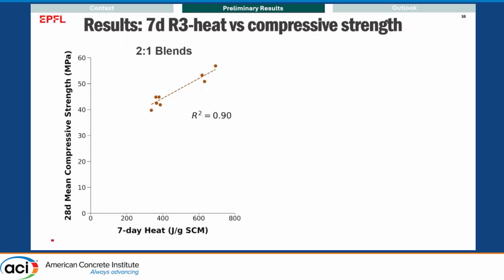Is there something evident from this? I think it is clear that we have clustering of data where three data points are on the top and the rest are in the bottom. I would like to make it clear that the top data points in the green actually correspond to the blends with the highest clay kaolinite content. So it implies that kaolinite content of clay dictates both the 7-day heat and compressive strength development for at least 2:1 blends. And all the other blends are with clay contents of 50% and 40% kaolinite content.